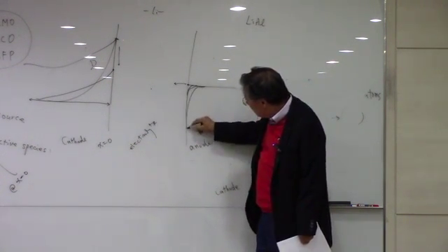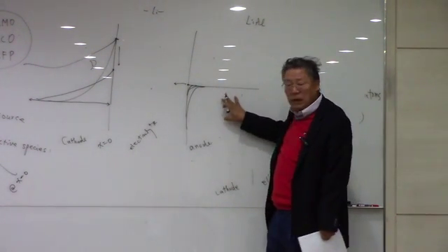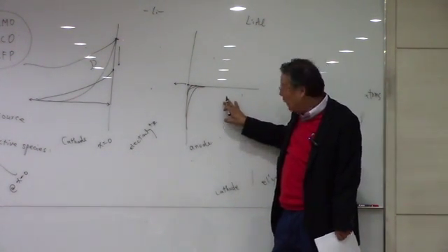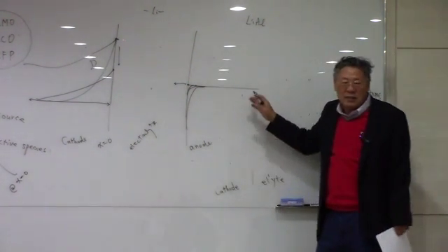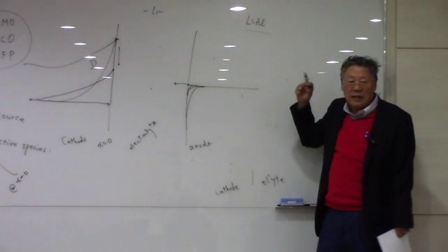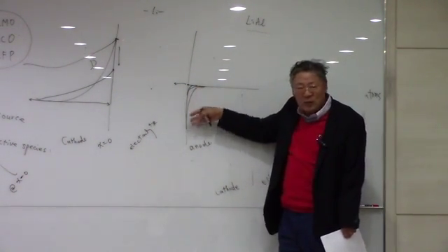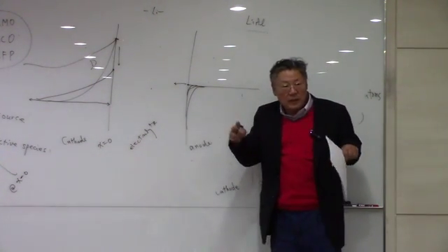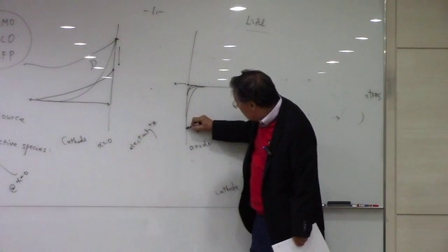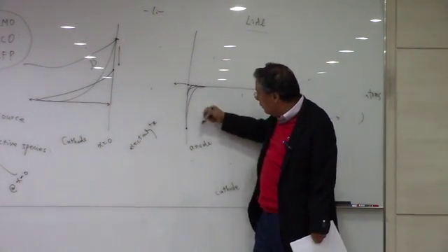Okay? As you take out the lithium from this material, the anode, if the activity is not 1 and it is a kind of compound like this, then the surface lithium concentration is going to be depleted as you proceed with the removal of lithium in the anode.